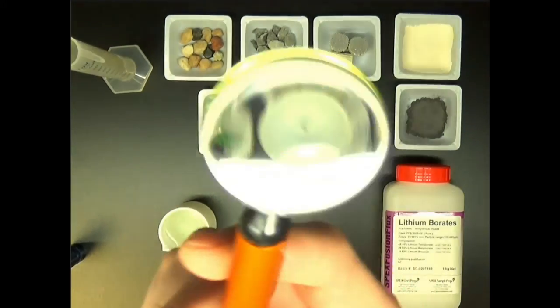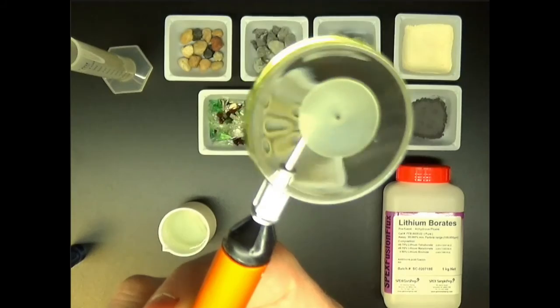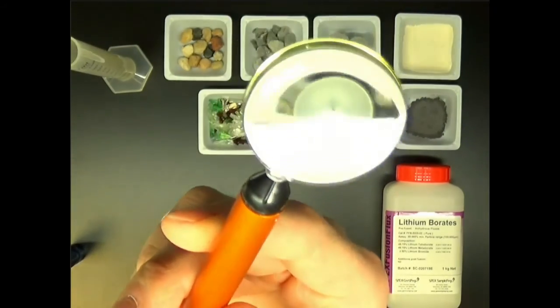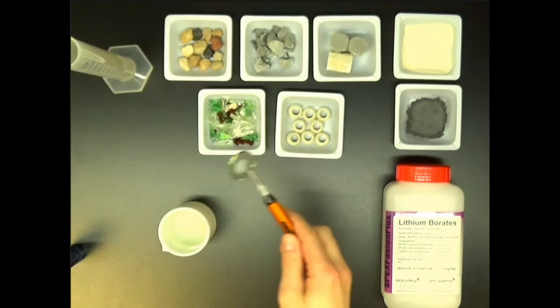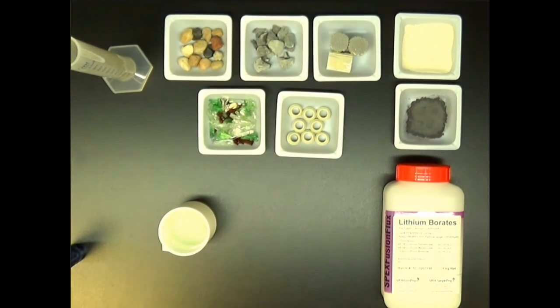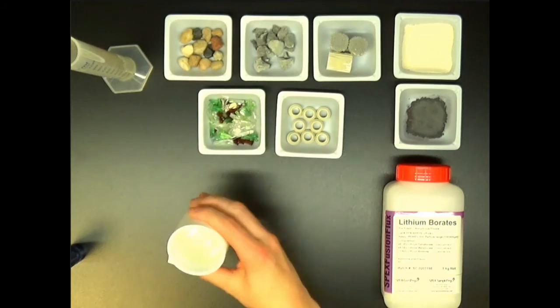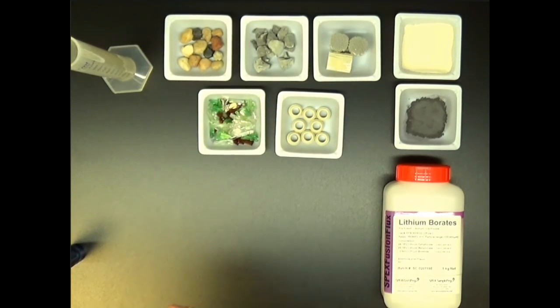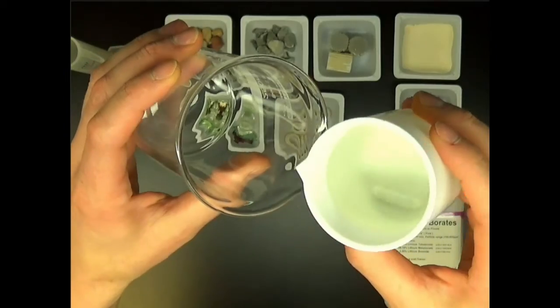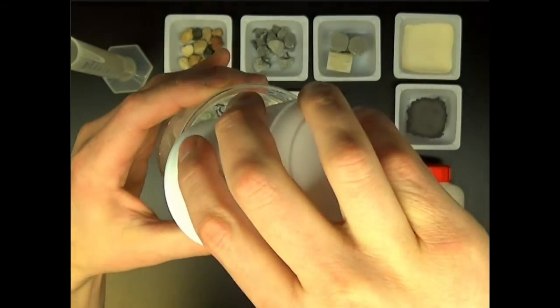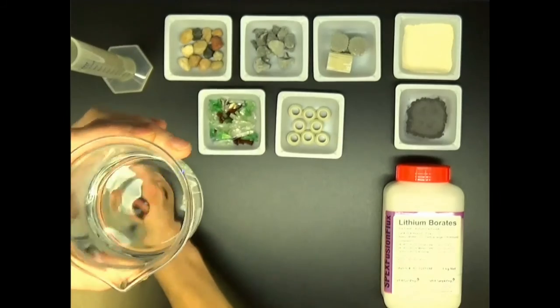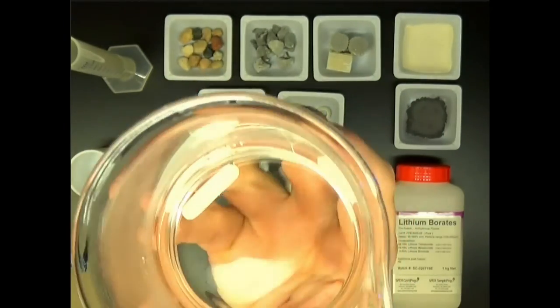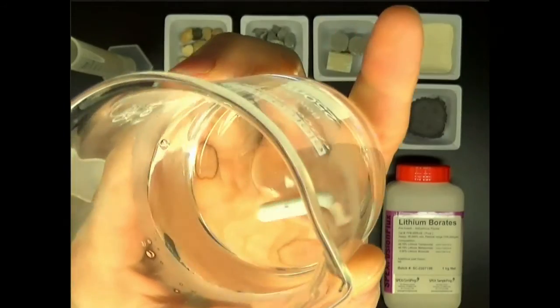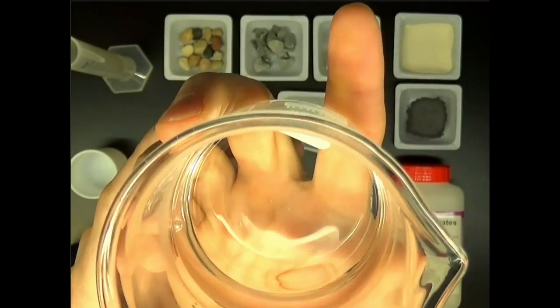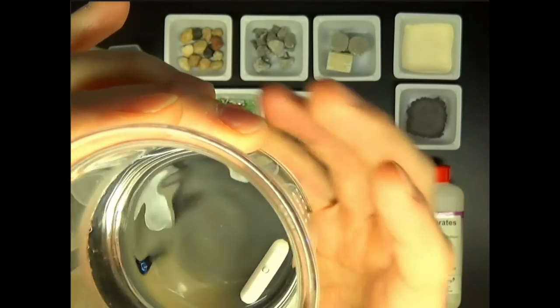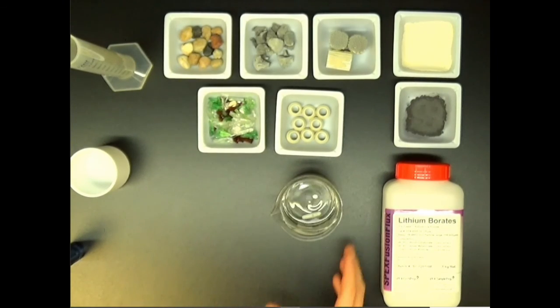I can show you better here the fuse bead obtained. So no undissolved particles, no visual defect. This is the kind of bead we want to reach, that will give optimal results on the XRF. For the solution, I will transfer right away into a clear container so you can have a better idea of what remains after 5-10 minutes of stirring. And it's already fully dissolved, so you will be ready to complete the volume and analyze this on ICP.